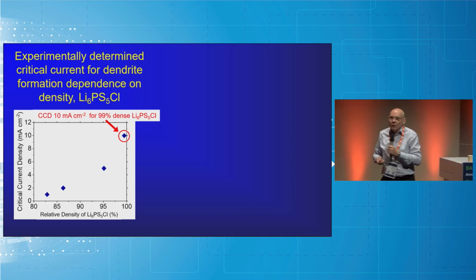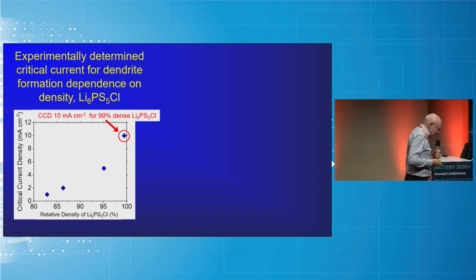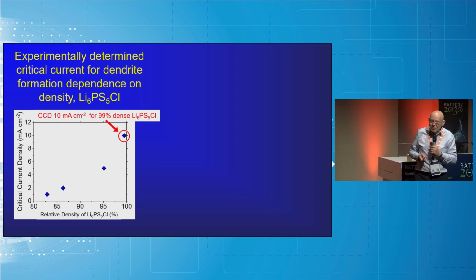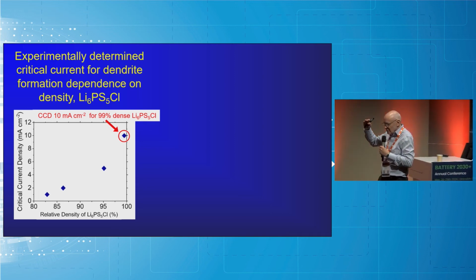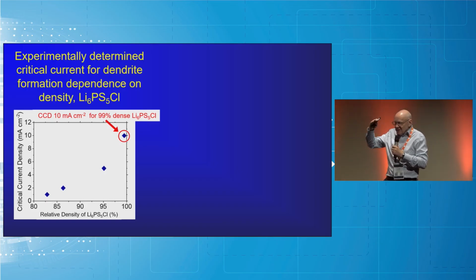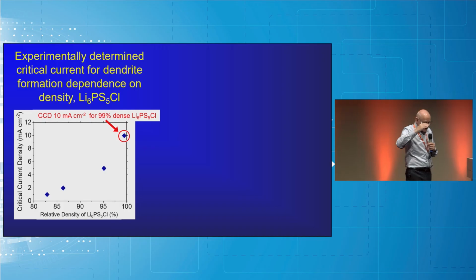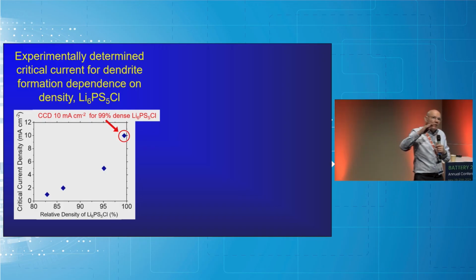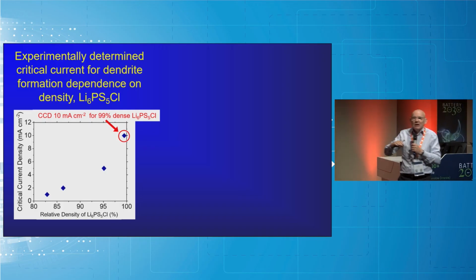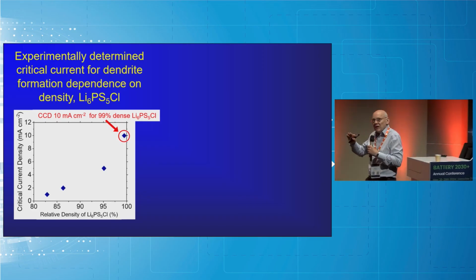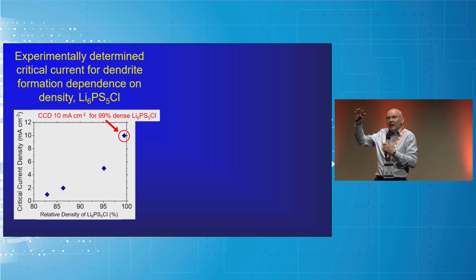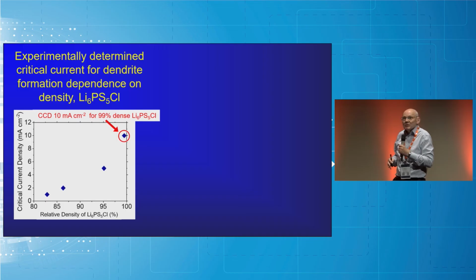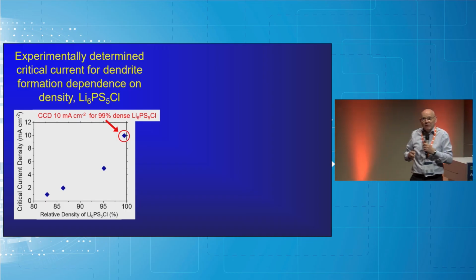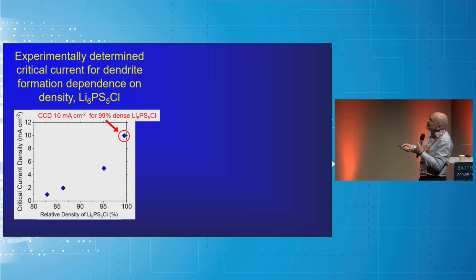Here's the result for argyrodite. Now, generally, the critical current density, that's the current at which dendrites start, is set for many ceramic electrolytes, including LLZO, the famous oxide, at about 1 milliamp, maybe 2 milliamps per square centimeter. For practical applications, you want to be north of 5. You want to be above 5, maybe 7 milliamps per square centimeter. That's proved really difficult. With argyrodite, here's the effect of densification.